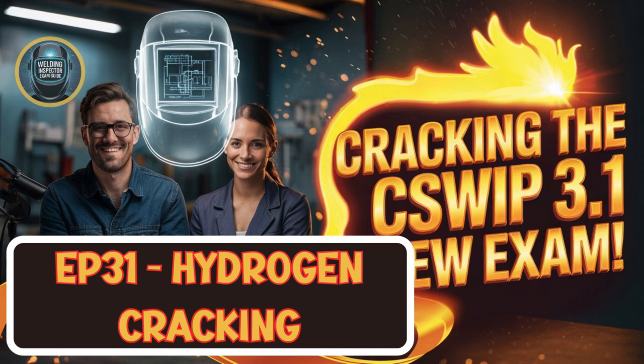So, given how insidious this is, what materials are we actually worried about here? Is it all metals? No, not all. It's mainly a problem for certain types of steel. Your basic carbon steels, carbon manganese steels, and then a whole range of alloy steels, low, medium, high alloy. Generally, we're talking about steels that have a ferritic or martensitic structure. Things like HSLA steels, high-strength, low alloy quench and tempered steels, TMCP steels, basically steels that can get quite hard if they cool quickly. That makes sense.